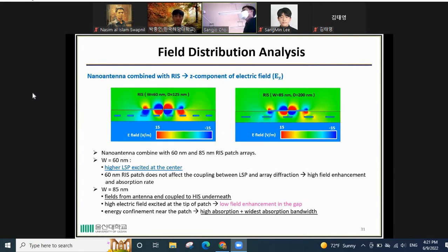And this is the field distribution analysis from the nano antenna combined with the RIS for 60 nanometer pads and also 85 nanometer pads. From the left figure for 60 nanometer pads, we can see that higher LSP is excited at the nano antenna center. And also with these 60 nanometer pads, the coupling between LSP and array diffraction is not in effect, so that high field enhancement and absorption rate can be maintained.